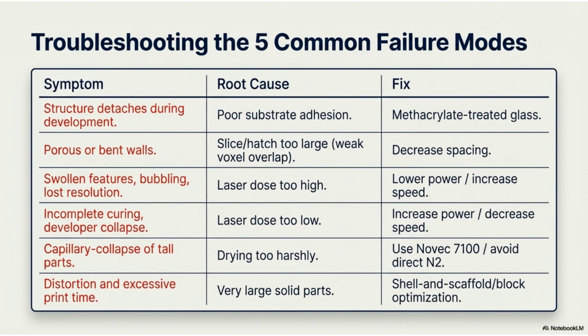Troubleshooting common failures includes addressing poor adhesion with treated glass, reducing slice/hatch spacing for porous walls, and adjusting laser dose for swollen features or incomplete curing. Use low surface tension solvents for fragile parts to prevent capillary collapse, and optimize large solid parts with shell and scaffold approaches.